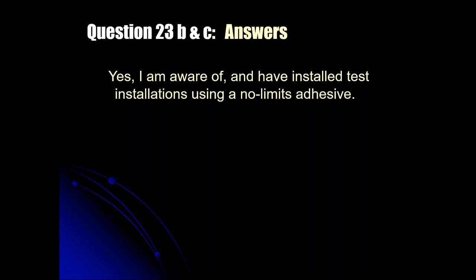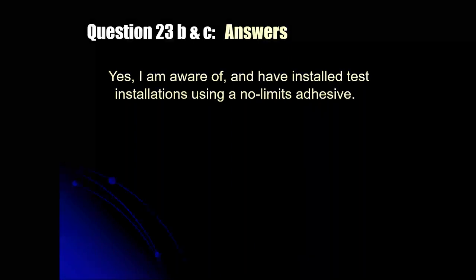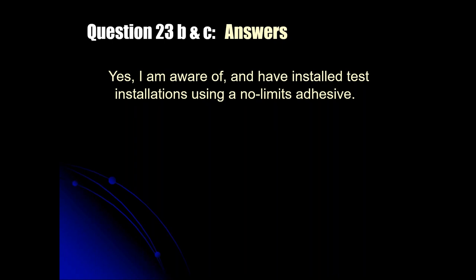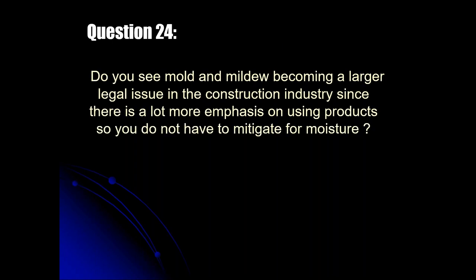It was plank flooring, so we would lift it. And there were actually droplets of water forming. There were no distortions in the flooring, and it was well adhered, but there was moisture, droplets, underneath or within that system. And of course, the hospital was concerned that if there's moisture, there's a potential for mold, and they would not go that route. But I am well aware that those systems exist.